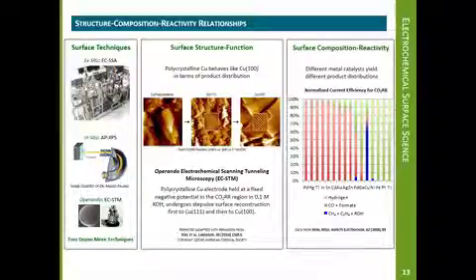Operando measurements conducted on the mixed, or polycrystalline surface show that under reaction conditions the surface is reconstructed naturally to the monocrystalline 1-0-0 arrangement. The importance of surface composition is highlighted on the right by the high yield of hydrocarbons by copper versus other transition metals.